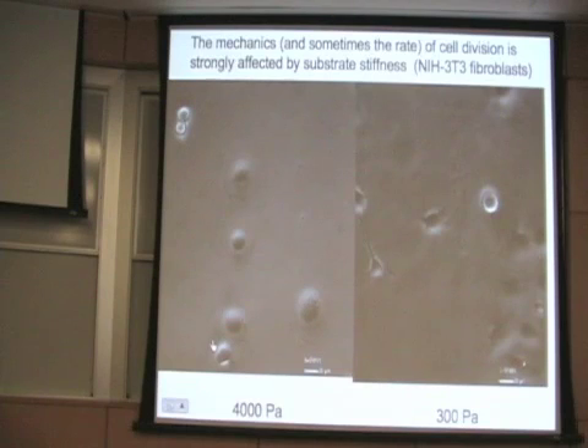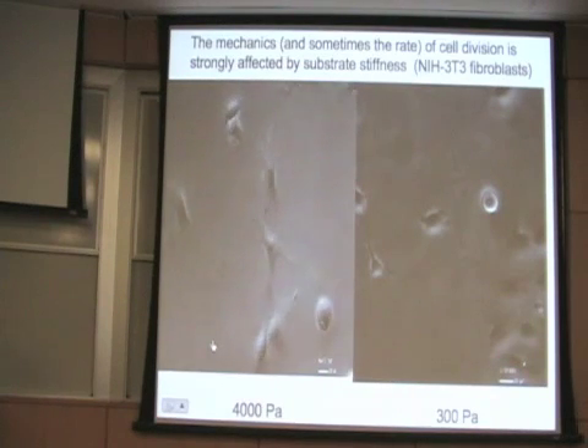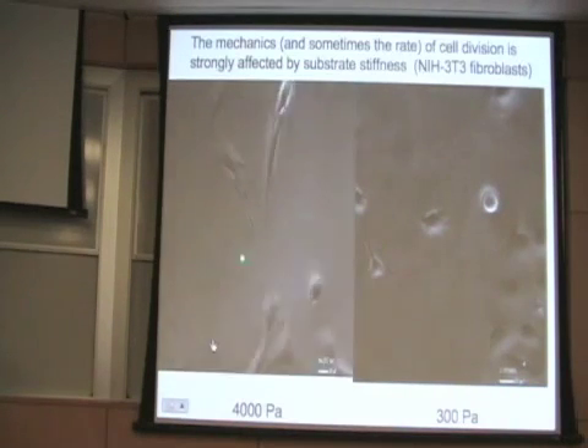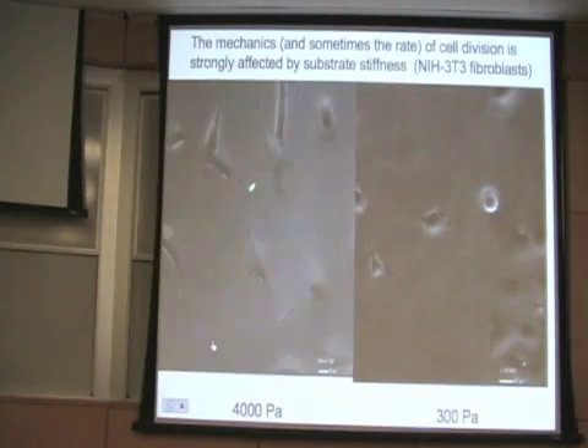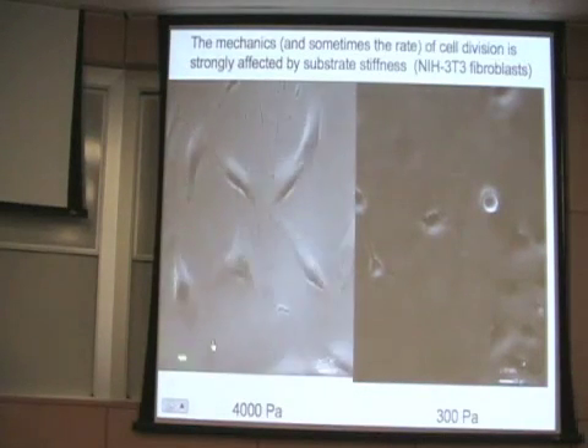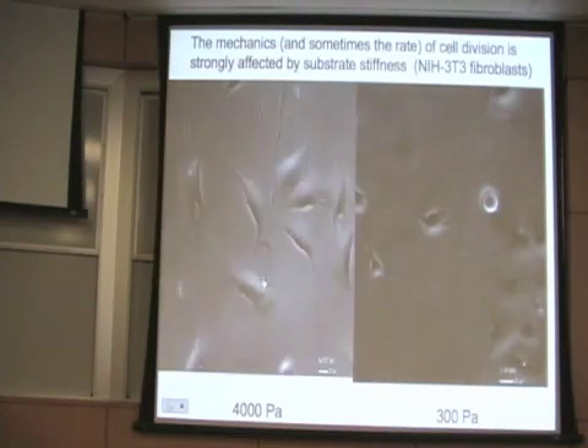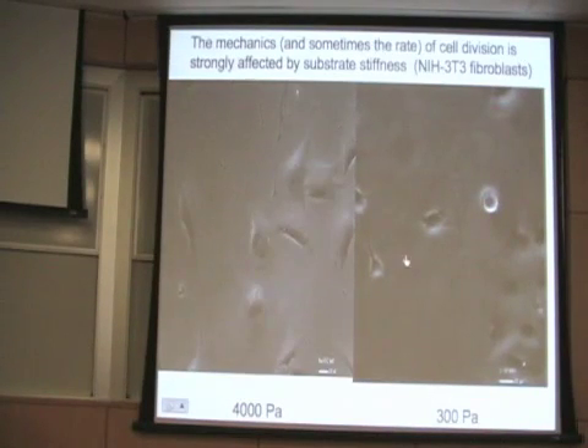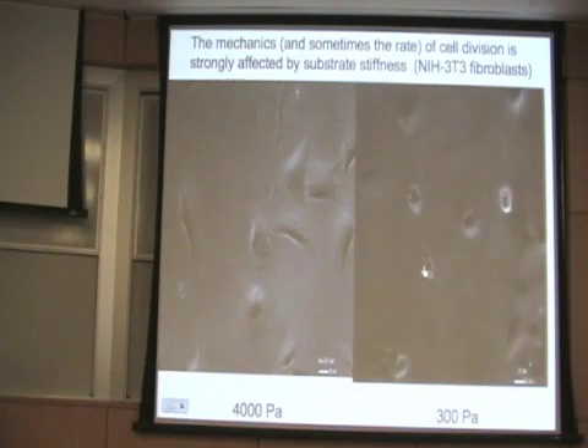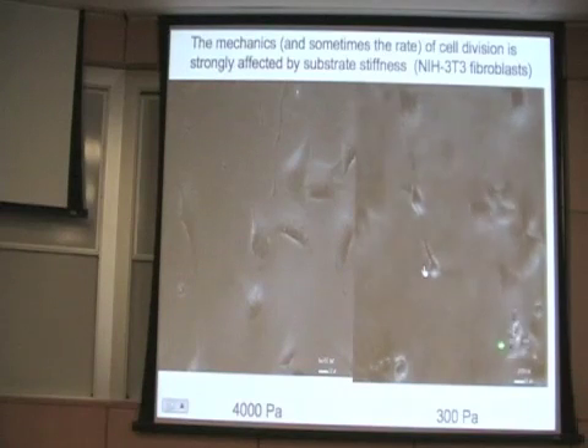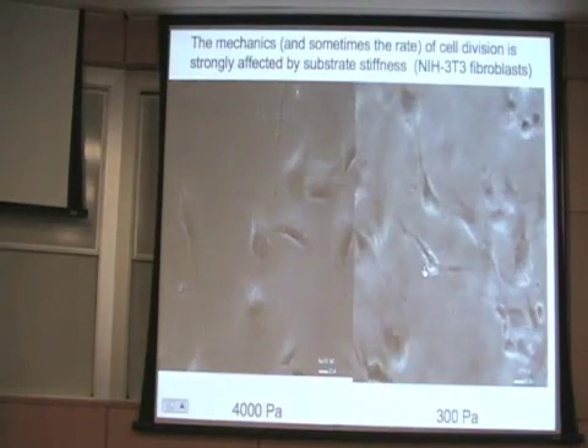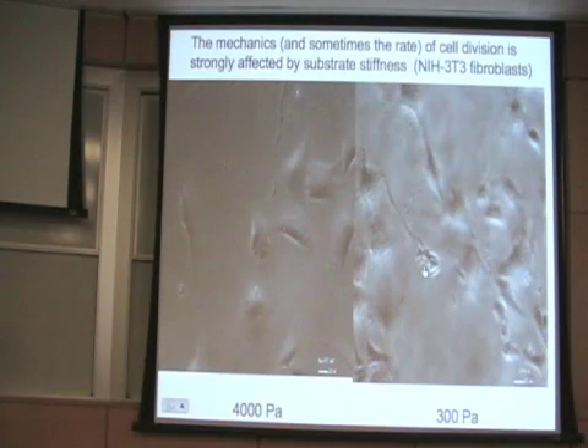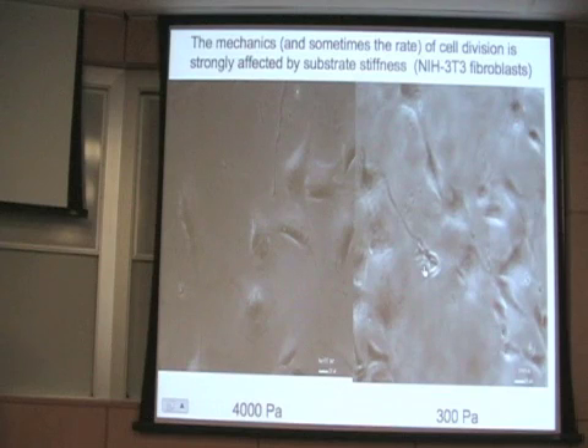So on the stiff part, the fibroblasts move around and they divide pretty much the way that they would on glass. I think if you showed this to somebody who worked on fibroblasts, there's nothing surprising here. This is what they look like on glass. But this is a gel that's about 4,000 Pascal. And this movie takes about a day and a half or so, or maybe somewhat less. Meanwhile, their neighbors on the other side of the gel are doing something completely different. Watch this guy. They round up and they explode. And they are not able to put these traction forces to get themselves to spread out in the spindle shape. They just develop internal tensions. They're still able to do mitosis, but their cytokinesis program is all messed up by not being able to distribute the forces.